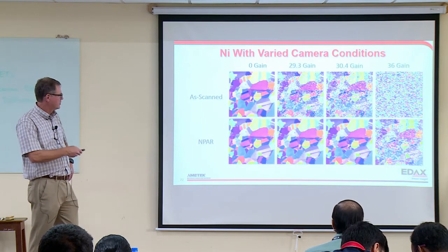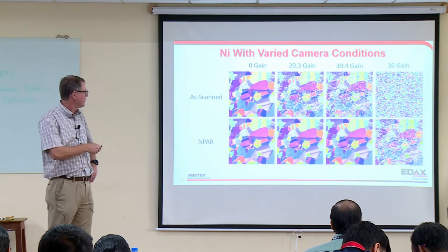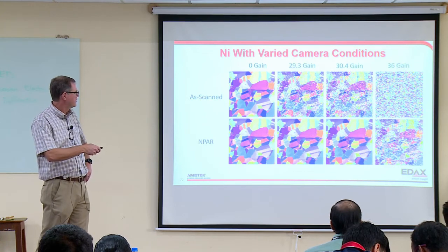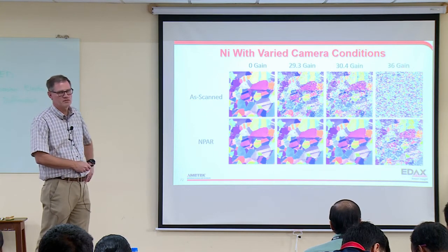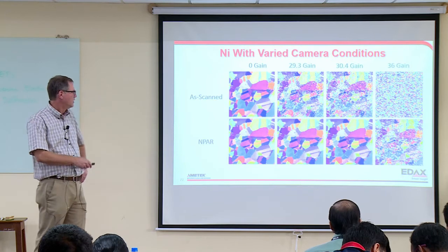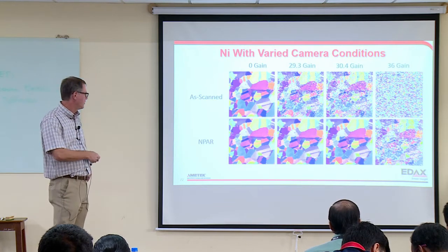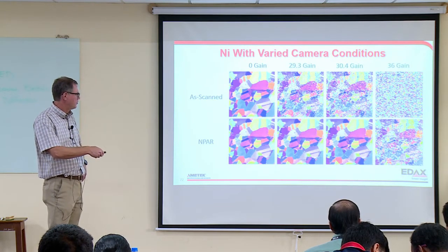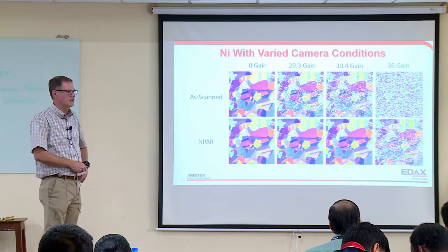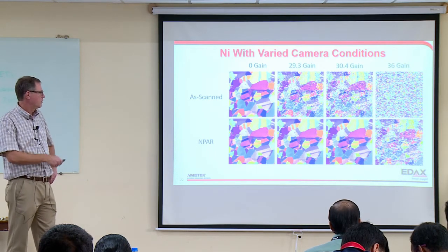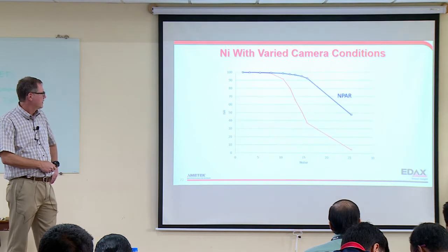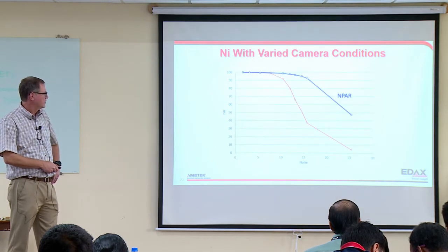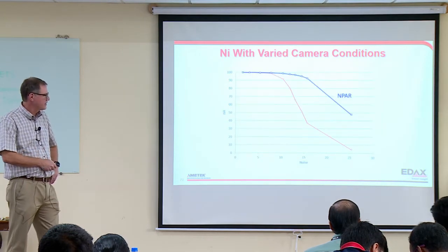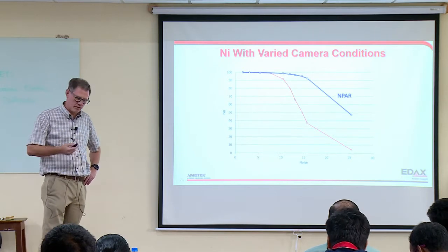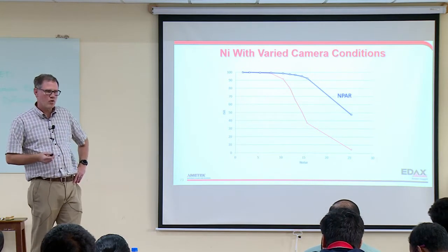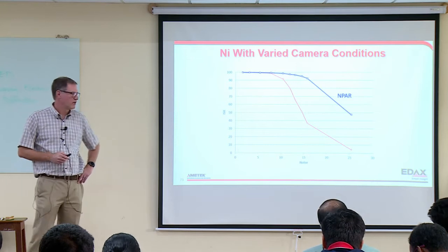So this is just 4 of those scans, 0 gain, and then one near the end. This is 36, the maximum gain on our CCD camera. So you can see the pattern's not very good. With NPAR, we do pretty well until we get here, and then it starts to fall off. With some cleanup, we can reconstruct some of it. And so you can see there the results are good, but what it does tell us is that if our noise is more realistic, the NPAR doesn't quite get us as much improvement as it did when the noise is artificial.